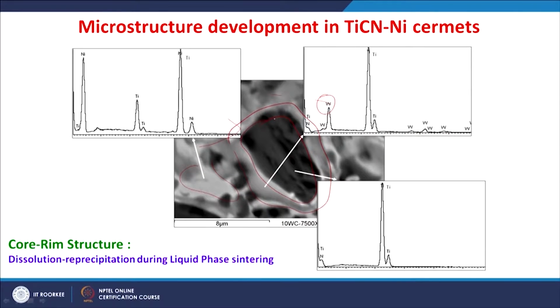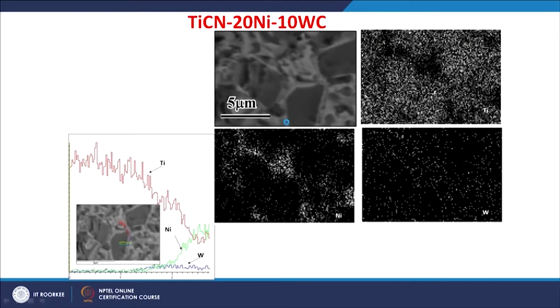So, the liquid wets the solid particles, and there is a dissolution of the solid, and in the process of sintering there is a precipitation. So, the undissolved portion is a core, whereas the precipitated portion is a rim. If you look at the X-ray mapping of this cermet material, you can also see a core region rich with tungsten and titanium, whereas the rim region has titanium, tungsten, carbon and nitrogen, and the binder region has nickel or titanium.